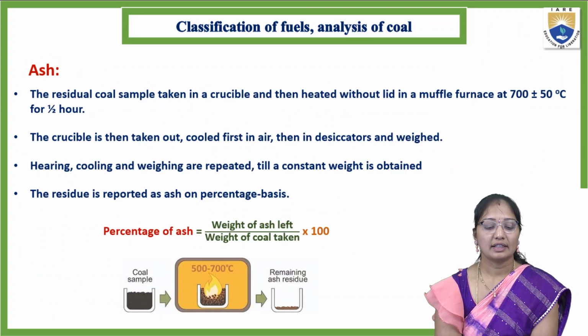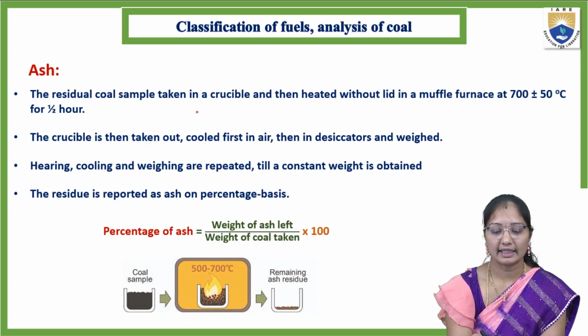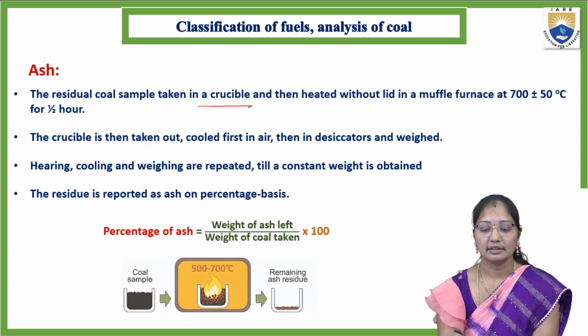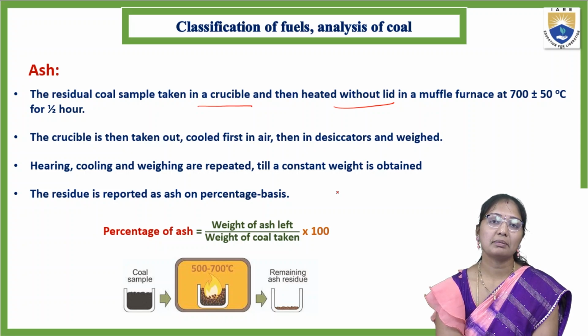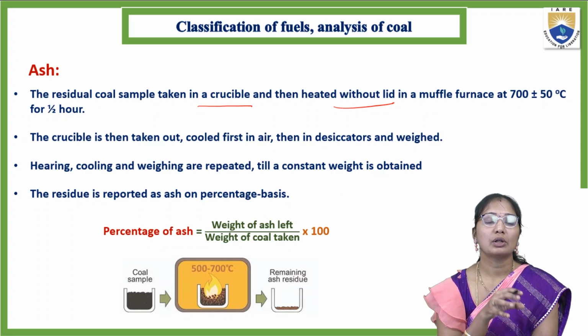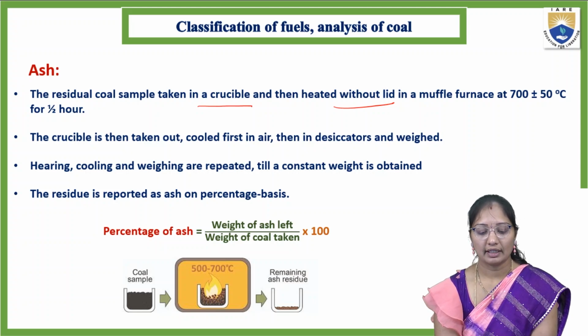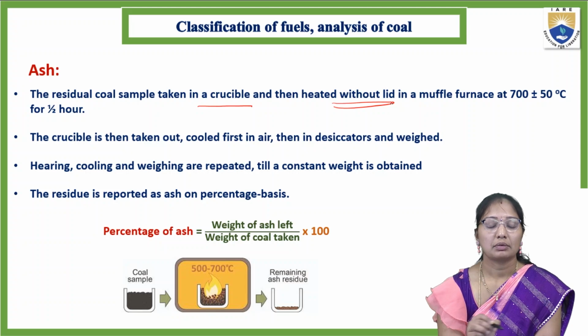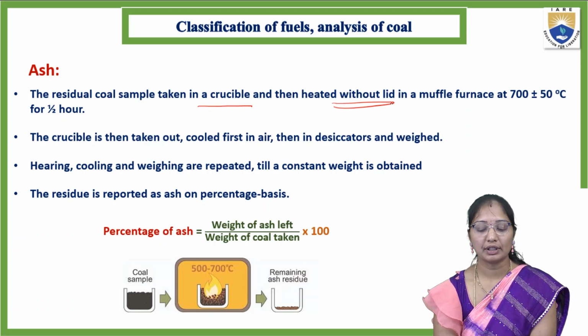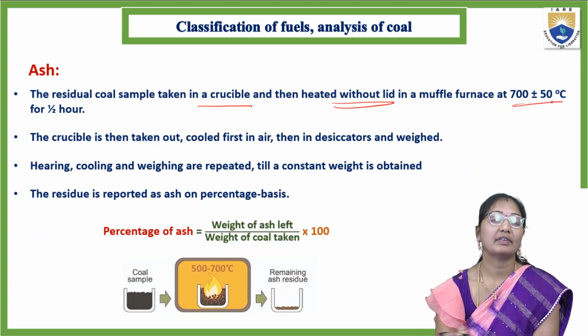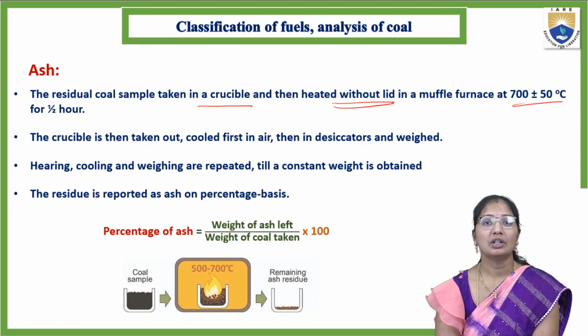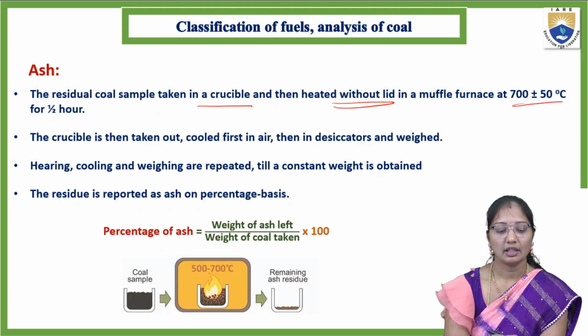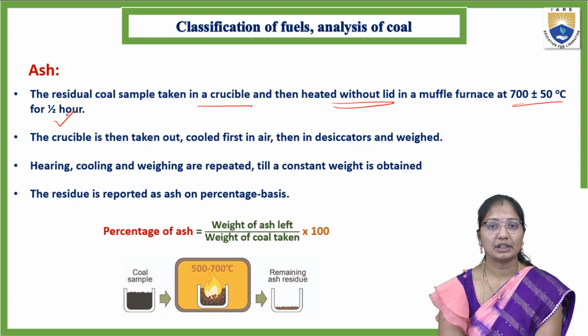Next is ash. The residual coal sample is taken in a crucible and heated without a lid in a muffle furnace. For volatile matter we closed the sample with the lid, whereas here we need not close the lid. We heat it without a lid in a muffle furnace at 700 plus or minus 50, around 700 degrees centigrade, for half an hour, 30 minutes.